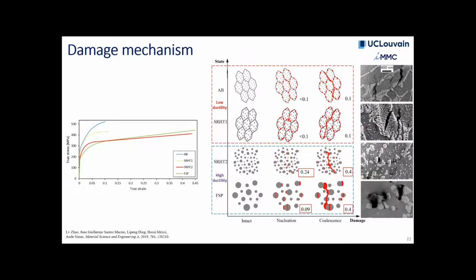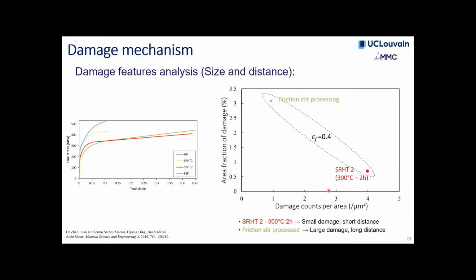So this network is not capable of holding very large deformations, and so it really fails quickly with very low strains. And so this leads to final ductilities that are very low, that you can also see here. And when we have this globularization, you can see that the nucleation of damage happens a bit later, and I'm going to make sense after of the difference that you have between these two conditions, FSP and stress relief heat treatment 2. And this leads to a much higher ductility in these alloys.